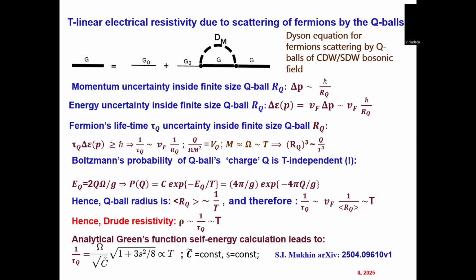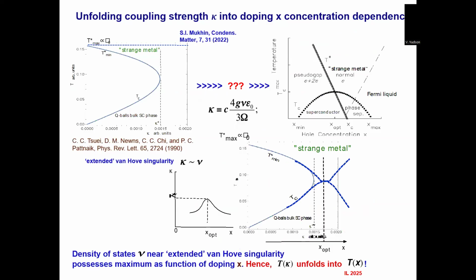The point is the following. In this strange phase diagram, when we are close to T star and when we are close to T star minimum, in both cases the size of the Q-ball diverges. So in between, there should be some percolation phenomenon. If you have something layered, there was a recent paper by one of our coworkers at the department, Pavel Grigoriev, who considered that a percolation cluster may appear first in the C direction and then faster than in the AB direction. So in principle, this may also be the case with the Q-ball gas when they start to percolate, but I don't know.